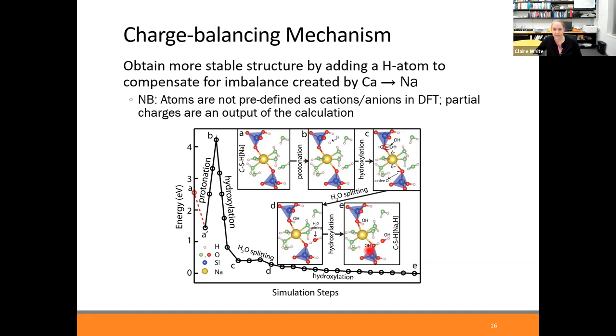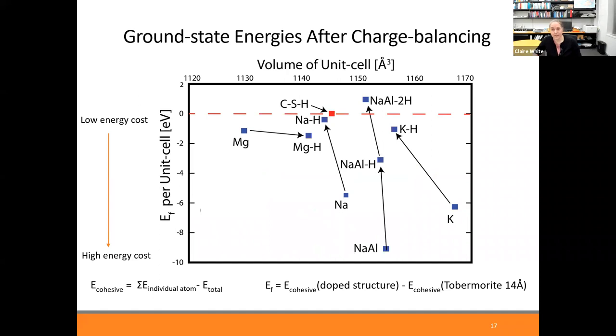And this also, what we found is that it wanted a symmetric charge distribution around the sodium. So we actually ended up with these two hydroxyl units forming, and then there's another hydroxyl floating around in the system. But this ended up with a more symmetric charge distribution around the sodium, which we think is leading to a more stable system overall. So if we do that for the structures that we looked at previously, it does have a very significant impact on the overall energy of the system.